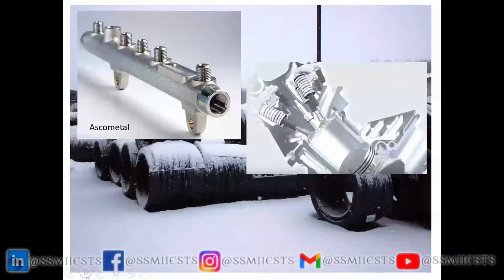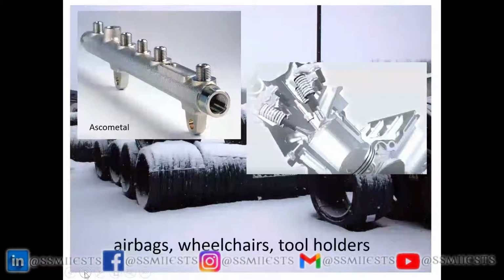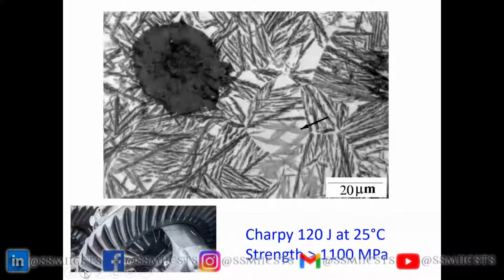people think of cast irons as being very brittle materials, right? And that is true if you have flakes of graphite and lots of cementite and so forth. But the same concept of a mixture of austenite and bainitic ferrite has been extended to cast irons as well. So we need to go to the next slide. So here you see what's known as austempered ductile iron. So there's a large lump of graphite there, but the matrix has been transformed essentially into a mixture of bainitic ferrite and austenite. And this cast iron, okay, remember this is cast iron. It has a toughness of 120 joules at room temperature and a strength in excess of 1100 megapascals. So this has opened up many opportunities to make complex components simply by casting, such as the component illustrated underneath.